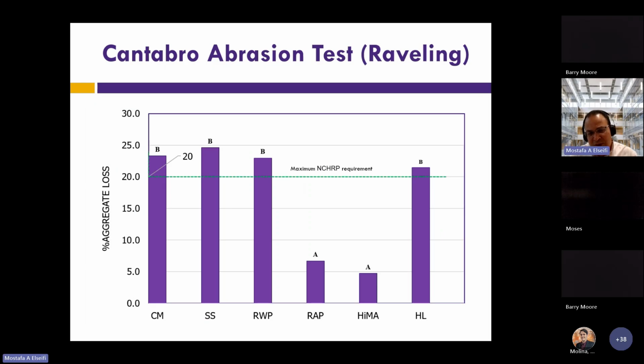In terms of the Cantabro test, this is the first mechanistic test that we did, you can see that there is a very significant difference. We have two main groupings. The RAP and the HiMA had a very low abrasion loss. On the other hand, we had the control mix, the steel slag, the recycled waste plastic, and the hydrated lime in the second grouping, which was above the 20% recommended by NCHRP. So you can see that we have two significant differences between these different mixes.